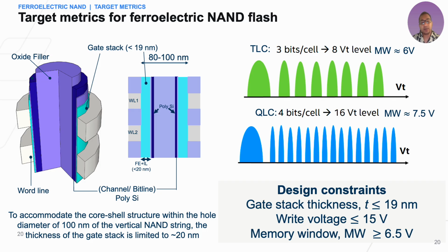So our group started working on the ferroelectric NAND flash concept in 2022. We set the targets from the geometry and operation of vertical NAND. The memory hole for a 3D NAND architecture is roughly 80 to 100 nanometers. So the complete gate stack needed to stay below around 19 to 20 nanometers. We wanted the program and erase within plus or minus 15 volts and the memory window above 6.5 volts to make 3 bits per cell or 4 bits per cell operation plausible. These are the design targets. They force us to pursue a thin stack with a large and controllable window.